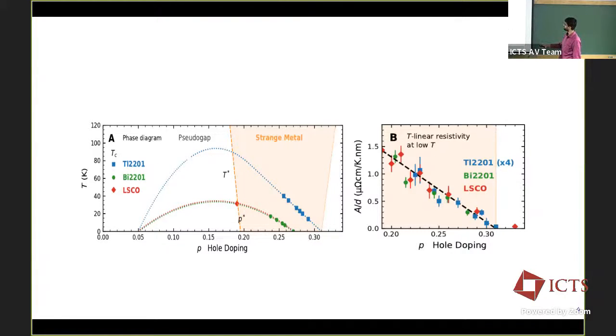But now people have observed that even at significantly higher doping, you find some anomalous transport, just like the T-linear behavior that I talked about yesterday. This is what is shown in this phase diagram schematically, and these are the observations of the coefficient of this linear-in-temperature resistivity term.